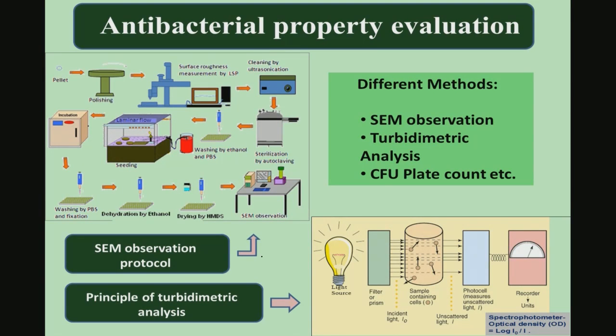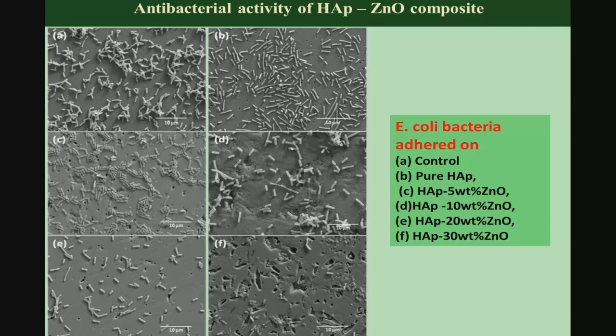For the antibacterial property assessment of zinc oxide composites, a standard methodology is used: polishing the sample, surface roughness measurements, cleaning, sterilization, washing by PBS, and then incubation at 37°C in a normal ambient atmosphere. Subsequently, turbidometric analysis is performed to quantify bacterial viability in the growth medium.